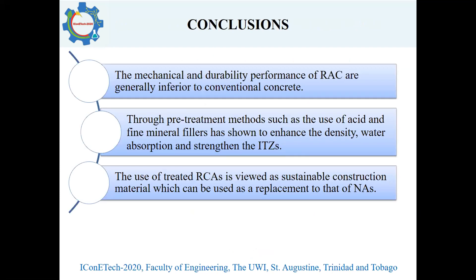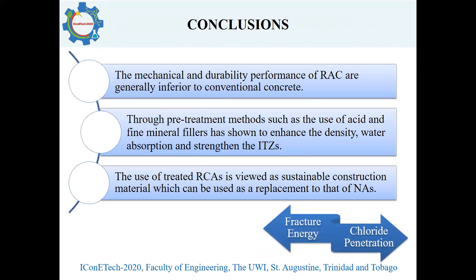In conclusion, the mechanical and durability performance of recycled aggregate concrete are generally inferior to conventional concrete. Pre-treatment methods such as the use of acid and fine mineral fillers have shown to enhance density, water absorption, and compressive strength. The use of treated recycled concrete aggregates is viewed as a sustainable construction material which can be used as a replacement for natural aggregates. Some gaps remain — there is a need for a more in-depth understanding of recycled aggregate concrete with respect to fracture energy and chloride ion penetration testing.